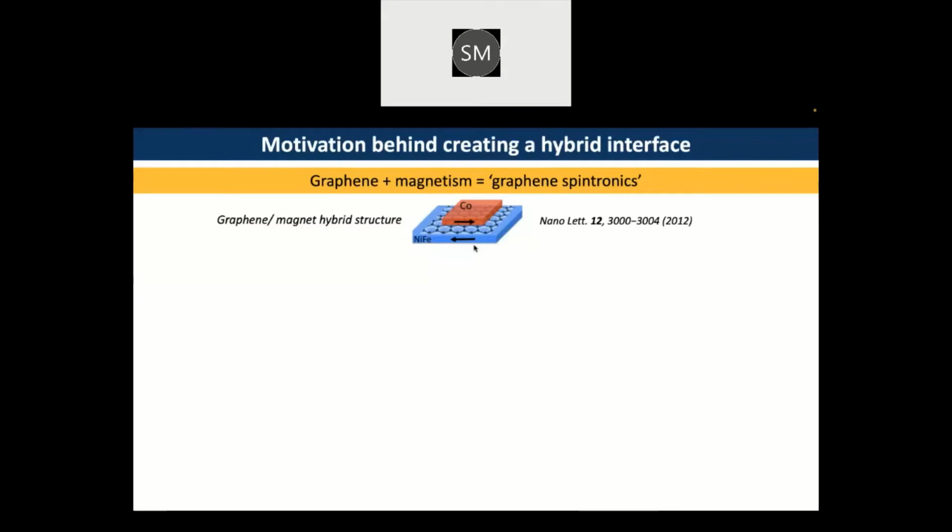Researchers have found that graphene maintains a give and take policy when it is hybridized with another material. It adds new functionalities into that material, and some of its own properties get elevated due to hybridization. Most importantly, the spin orbit coupling, which is weak for pristine graphene, becomes very strong when it is adjacent to another magnet. Also, reduction of magnetic moment due to proximity effect is observed.